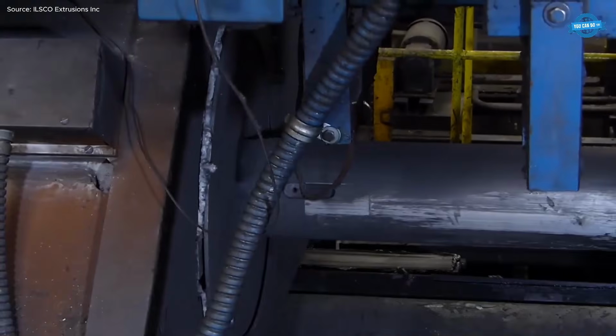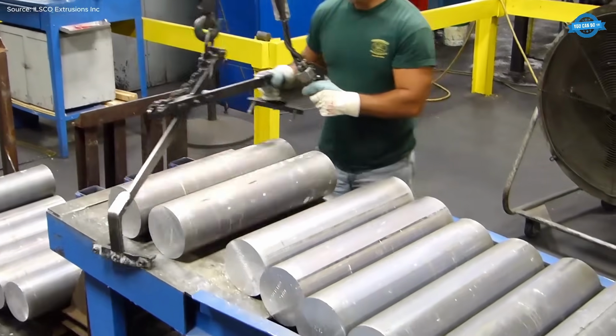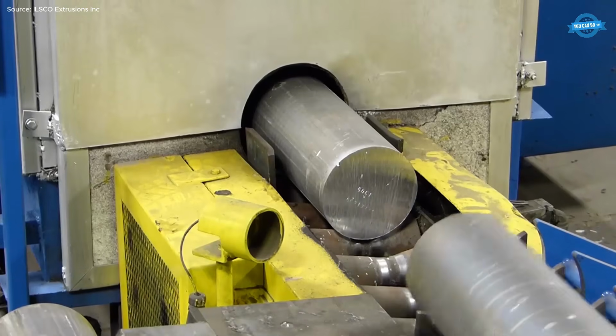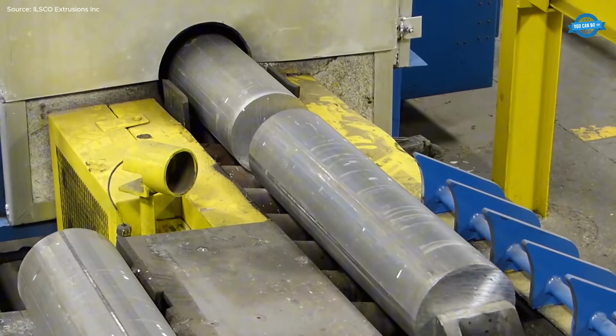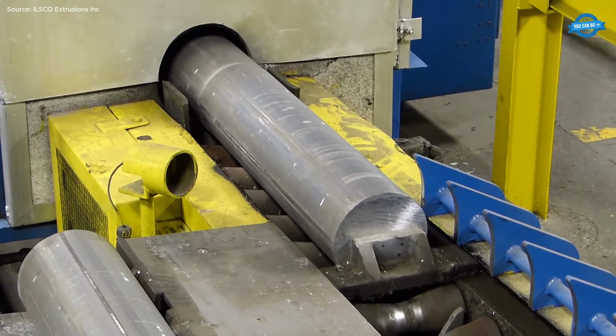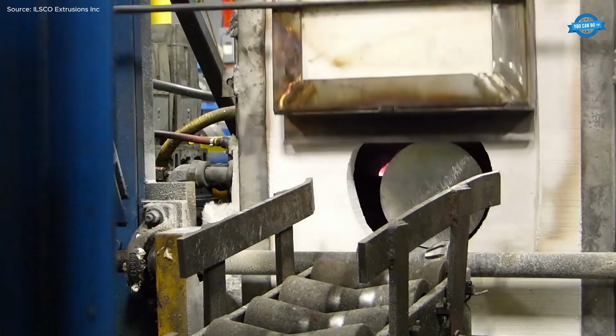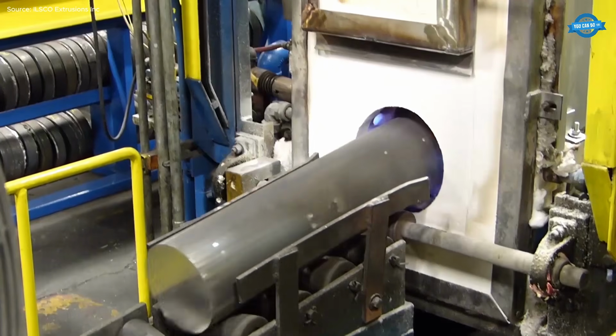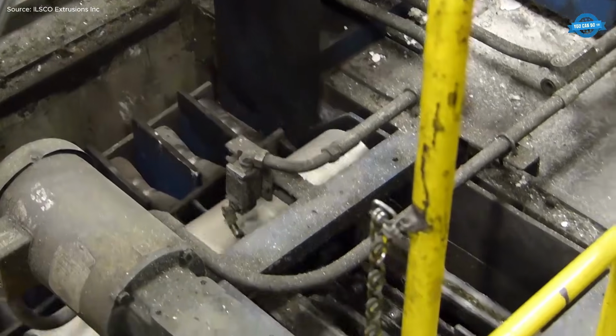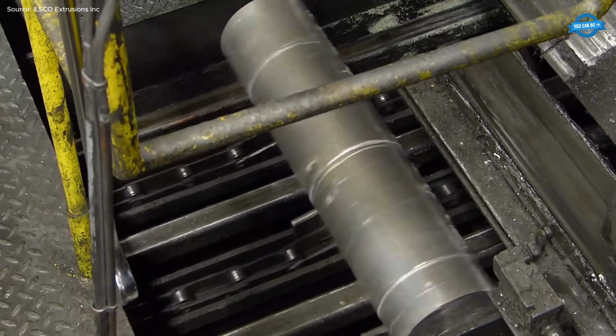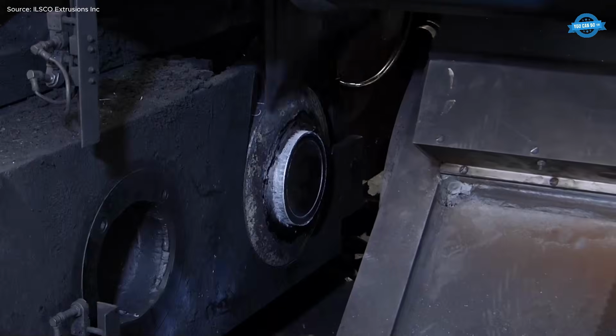The process begins with billets, cylindrical pieces of aluminum alloy, pre-cut to a uniform length. These billets are heated to around 900 degrees Fahrenheit in a billet furnace until they become malleable but not molten. Once ready, the billet is transferred to the extrusion press, where a hydraulic ram forces the metal through a precision steel die. This die determines the shape of the final profile.